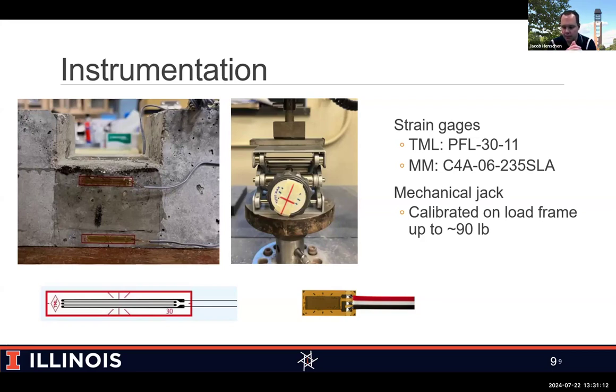And I've done this numerous times where you apply a thin layer of epoxy. That's why the surface looks wet there. And then we apply our strain gauge on top of the epoxy. The epoxy gives us a nice flat, consistent surface to bond our gauge to. And then we can also use just the standard cyanoacrylate cement to fix the gauge.